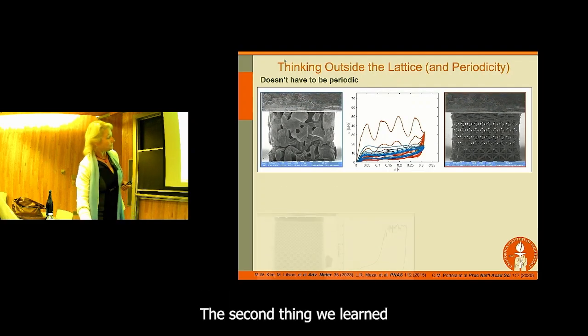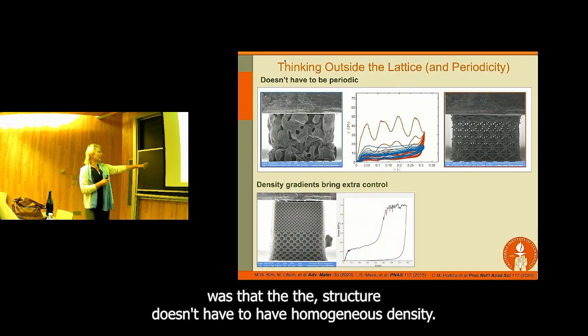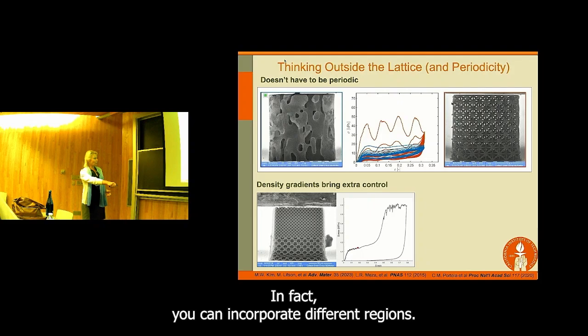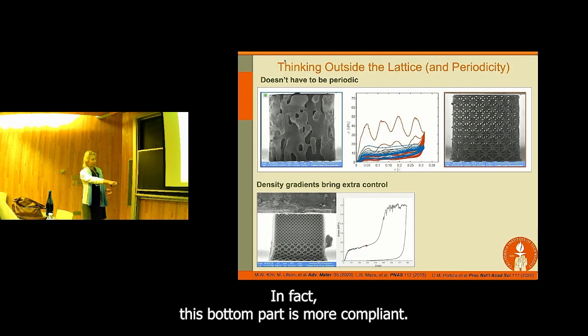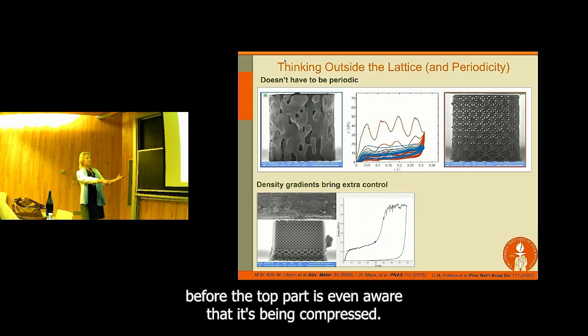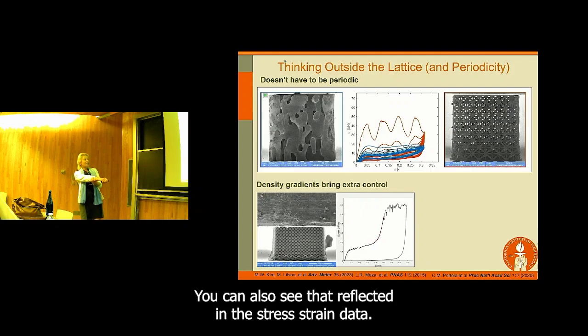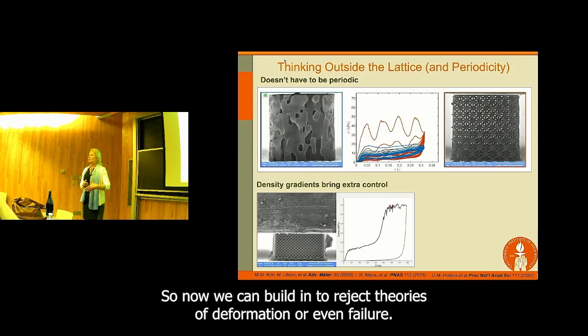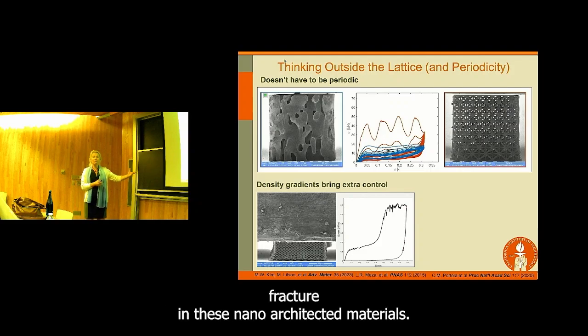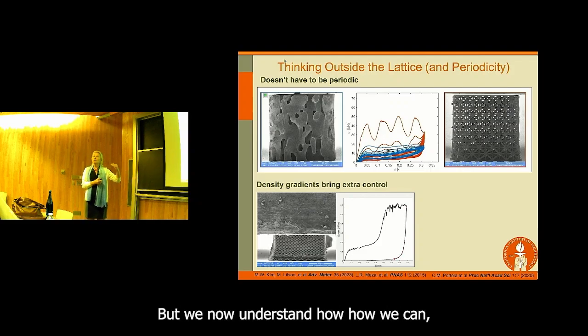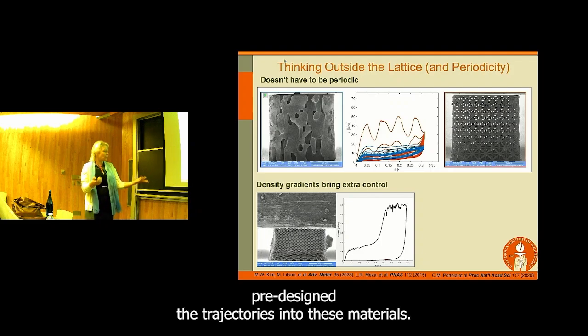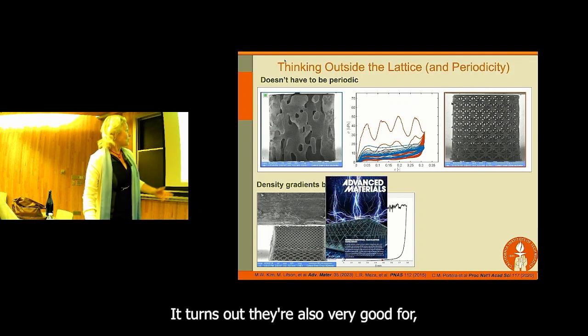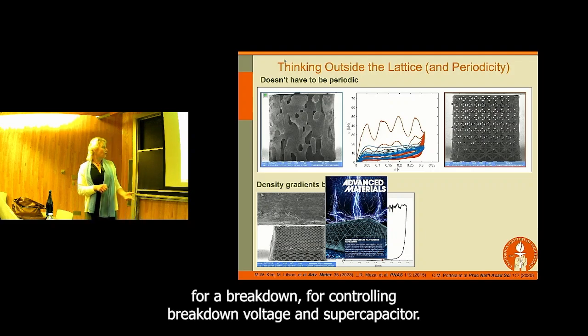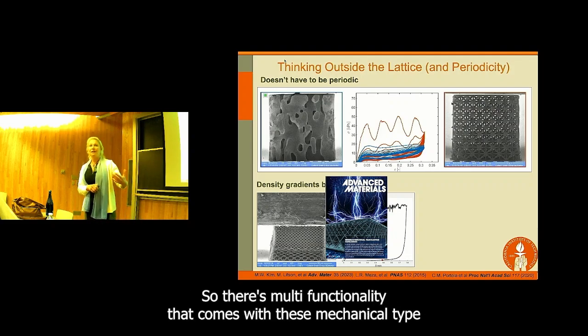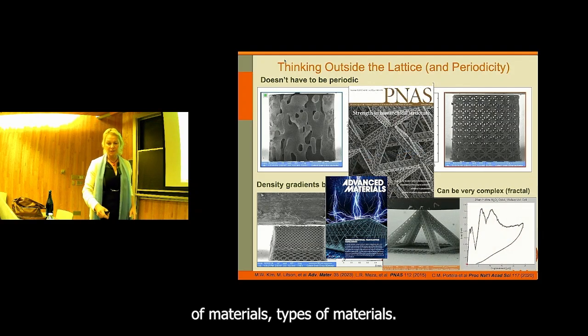The second thing we learned was that the structure doesn't have to have homogeneous density. In fact, you can incorporate different regions. This bottom part is more compliant, so it's fully densifying before the top part is even aware that it's being compressed. You can also see that reflected in the stress-strain data. So now we can build in trajectories of deformation or even failure. This is something new to us, studying fracture in these nano-architected materials. But we now understand how we can pre-design the trajectories into these materials. It turns out they're also very good for controlling breakdown voltage in supercapacitors. So there's multifunctionality that comes with these mechanical types of materials.